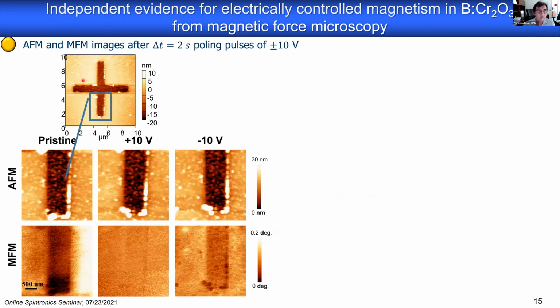Okay, but more convincing would be a completely independent measurement, something that has nothing to do with our transport data, and there we teamed up with Alexei Gruverman, who also does magnetic force microscopy. And here you see an atomic force microscopy image of our Hall bar, here magnified. You see that leg. And now you see what happens in the magnetic force microscopy contrast. When you apply positive voltage, the contrast disappears. And when you apply a negative voltage, the contrast reappears, and so forth. That is another indication that indeed this effect, the signal we see, is magnetic.